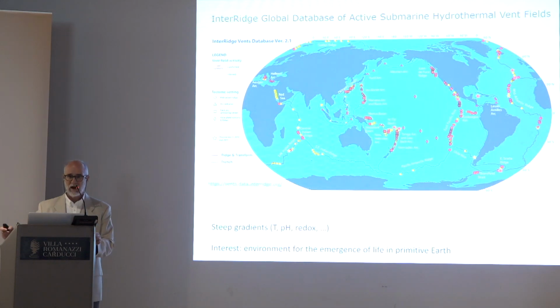In this map, you can see the hydrothermal vents known, and also those that are inferred. And you see they are aligned along the, for example, the Ring of Fire in the first figure. In all of them, we have steep gradients: steep gradients of temperature, pH, redox, concentration. That means energy. And life needs energy. So here is the great interest in this environment for the emergence of primitive life.